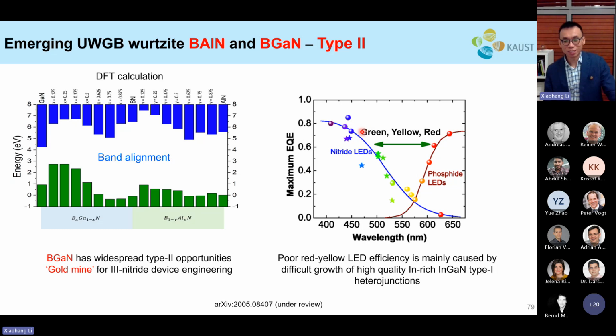Many years ago, when I was a grad student, people talked about the green gap, right? Because if you want solid state lighting, you want an efficient green light. And I think Osram has done a lot of great work in that area, including LEDs and lasers. But now we also have the red gap, or the yellow gap, red and yellow gap. This low efficiency is primarily caused by the difficult growth of high quality, strain engineered, indium-rich InGaN type 1 heterojunctions, right? So can we utilize the type 2 heterojunction for the red or yellow LED?